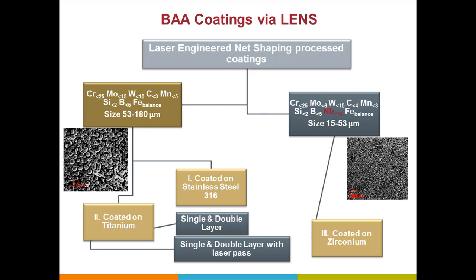So what we did is we got commercially available 2 different chemistries, both of them iron based. There's no particular fascination why iron based, it's just what we could get hold of. This particular chemistry does not have niobium, this one has niobium, and we use 3 different substrates. One is stainless steel 316, widely used, which is already corrosion resistant. We can put a bulk amorphous alloy coating or structure and see if we can change that.